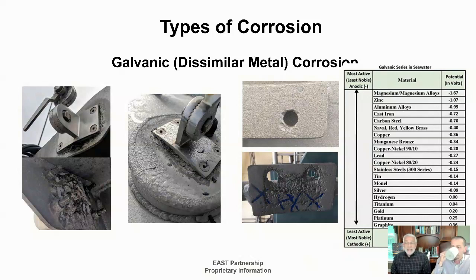Now galvanic. Galvanic is becoming more and more of an issue because we want things lighter and faster, so we start going to lighter materials. In our minds, aluminum is corrosion resistant. I could take a hunk of aluminum, throw it outside on the beach with salt air, come back in 10 years, and there's that piece of aluminum. I could do the same thing with stainless steel, but if I put those two together, look at the galvanic scale: aluminum is way up here, in the least noble area, and stainless is down midway through the galvanic series. The further apart these materials are, the more rapid the corrosion rate will be for that anodic piece.